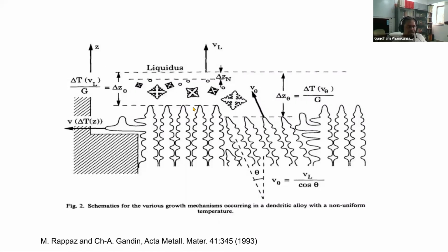So this map is something that I want you to relate with what you have seen in the video in the beginning of the lecture. I have shown you that you can have cellular microstructure growing, and you can also have nucleation of grains in the front, which will actually settle down and form equiaxed growth. So there is a competition between the columnar growth and equiaxed growth.